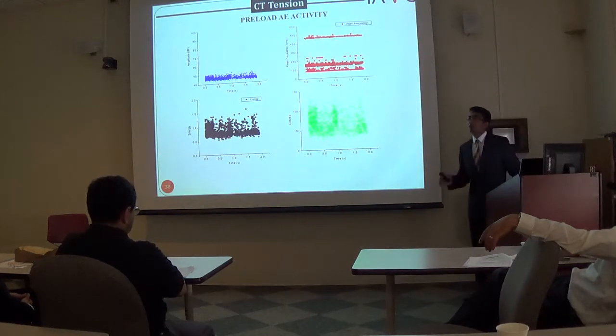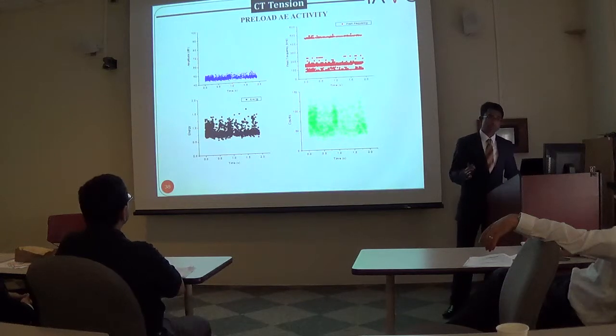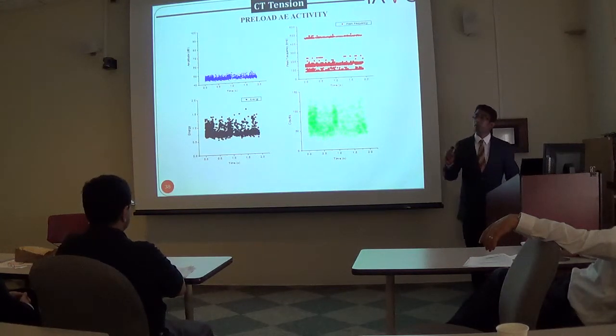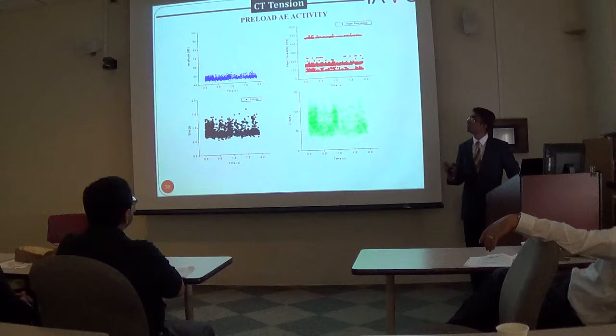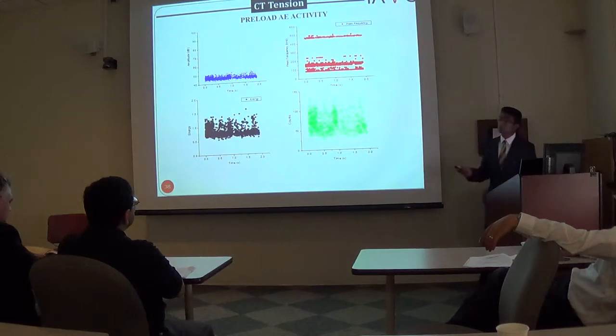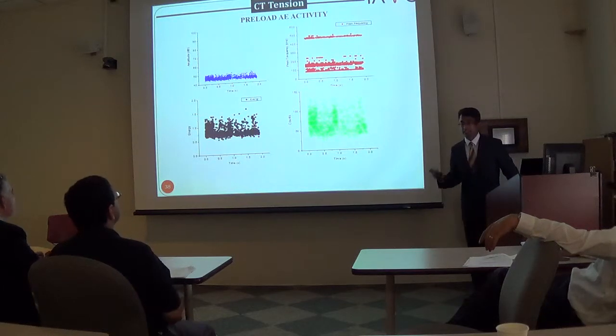So, before actually experimentally testing the CT specimens, a preload of about 100 Newton was applied on the CT specimen. And at this load, we still could pick up a lot of AE activity, and these are actually the noise sources in the environment.